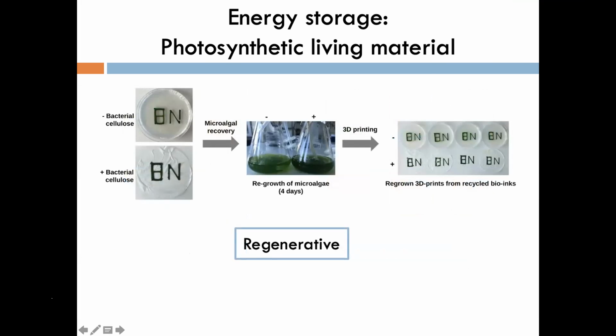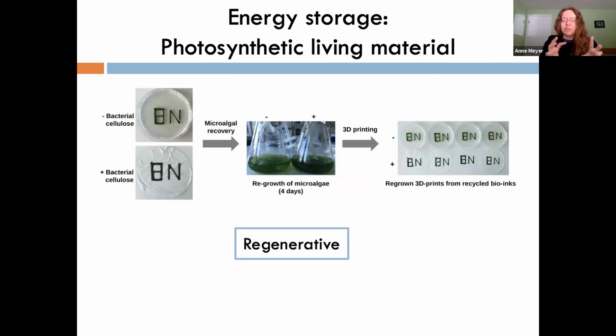And you know how our bacterial nacre was remoldable, this is regenerative, right? So here's an example. We took our 3D printers, we printed the letters BN, for our department name, in microalgae. We grow it for a few days to get nice and green. Then we can recover the algae. So we can dissolve the letters. We grow the algae for a few days, and then we can 3D print and make 4 times as many letters as we started with, right?